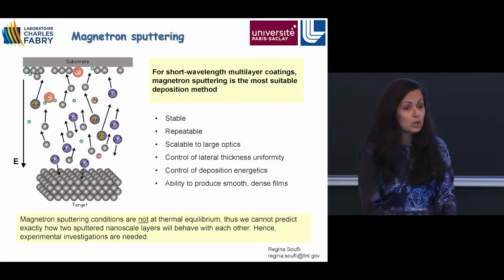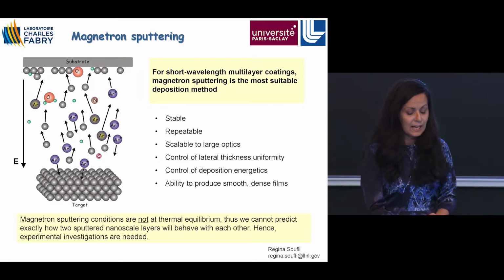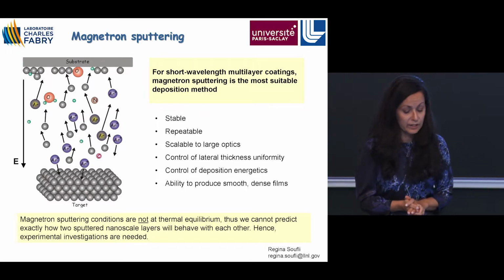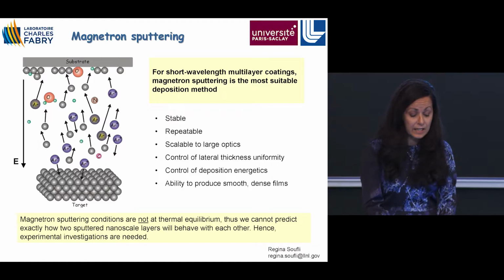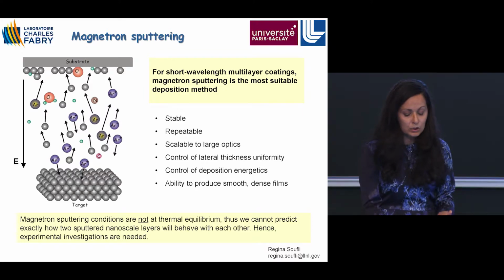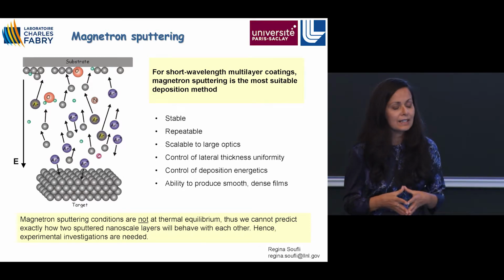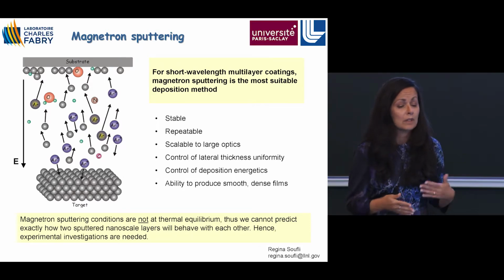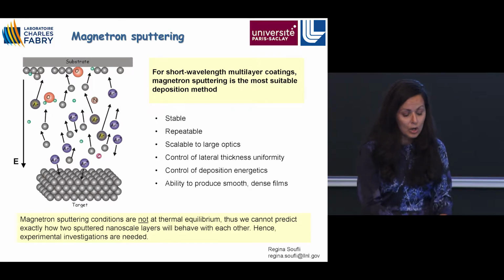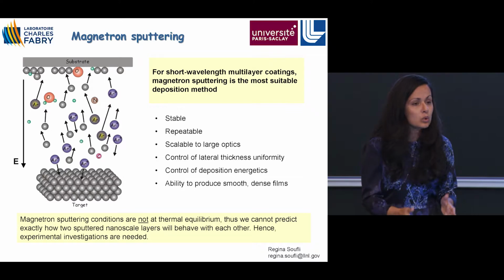This technique has been maturing for the last 30 years. And without getting into details, it has all the right properties to make this type of coating for this wavelength region. I should emphasize here something very important that often comes up as a question. The conditions during magnetron sputtering are not at thermal equilibrium. Therefore, we cannot predict exactly, theoretically, using thermodynamic codes and other theoretical calculations, how two sputtered